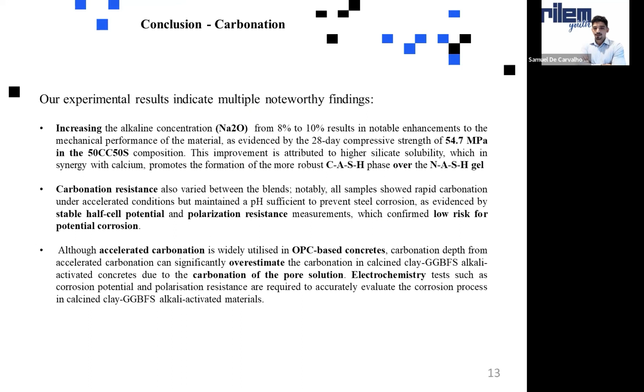As I said before, increasing the alkaline concentration to 8 to 10% really improves the mechanical performance. You have after 28 days something around 54 MPa for the composite with 50% of calcined clay, 50% of GGBFS. Also, the carbonation resistance shows that even under accelerated and natural conditions, the pH is still maintained at a really high level, which prevents steel corrosion. And you proved that also with the stable half-cell potential and polarization resistance tests, which confirm that there is a really low risk of potential corrosion.